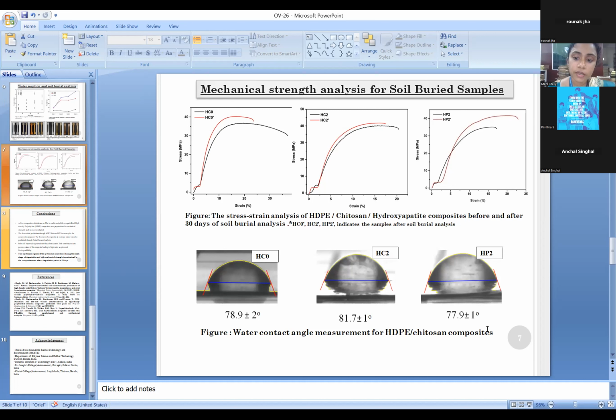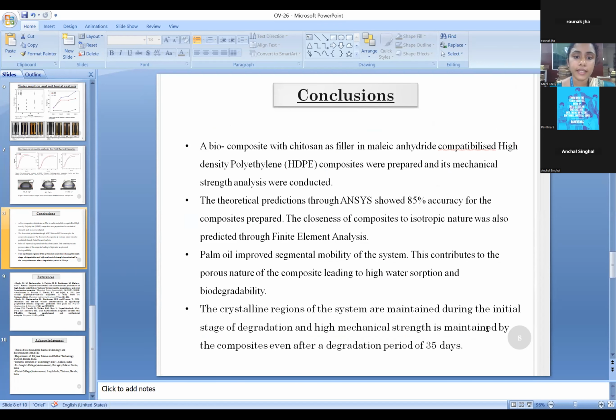And the water contact angle studies also show that the HC2 system has better filler matrix interaction and has decreased the degradation rate in soil. So I am concluding that here I have prepared a biocomposite with chitosan as filler in maleic anhydride compatibilized HDPE system and its mechanical strength was analyzed. The theoretical studies were done using ANSYS analysis and it has shown an accuracy of 85%. The closeness of the composite to isotropic nature was also predicted with the help of finite element analysis.